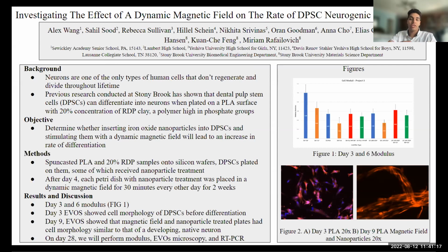After day 4, each Petri dish that had nanoparticles was placed in a dynamic magnetic field. Each sample was exposed to the same conditions with 30 minutes of the dynamic magnetic field every other day for 2 weeks. And we then compared the cells with dynamic magnetic field treatment to the cells without dynamic magnetic field treatment. And I'll pass it over to Alex to discuss some of the results.